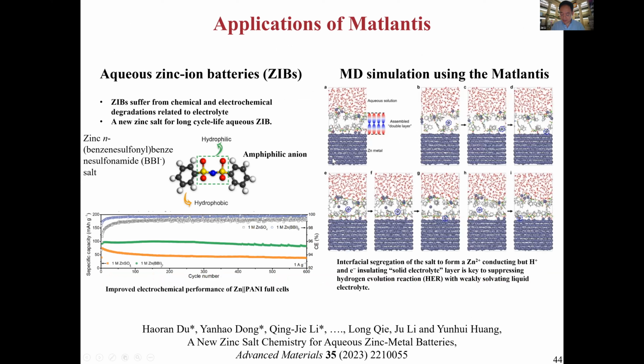So to show you some initial applications, this is a new salt for aqueous zinc-ion battery material. Zinc-ion batteries, zinc metal batteries, have this hydrogen evolution problem because the zinc metal potential is actually below the hydrogen evolution potential. So what people have developed experimentally is this benzene sulfonyl benzene sulfonamide anion, which is an amphiphilic anion. It has a hydrophilic part, the core, and then two hydrophobic sides.